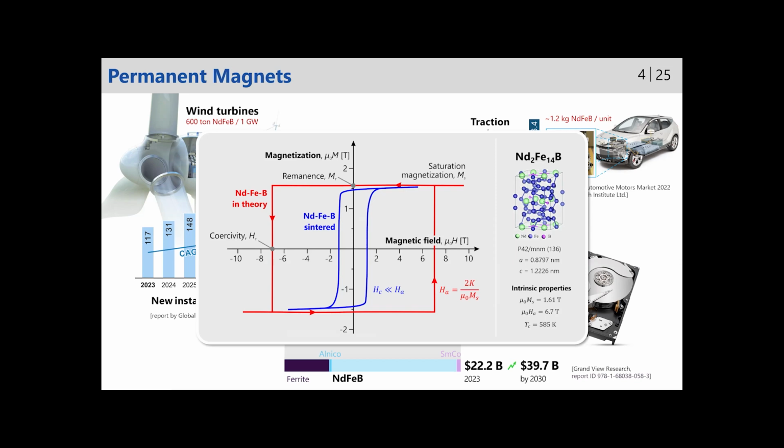Maybe the origin of this discrepancy is defects. Indeed. It means that we should introduce defects into our models carefully: intergranular phase, misorientation of the grains with respect to the crystallographic texture axis, and some other defects.